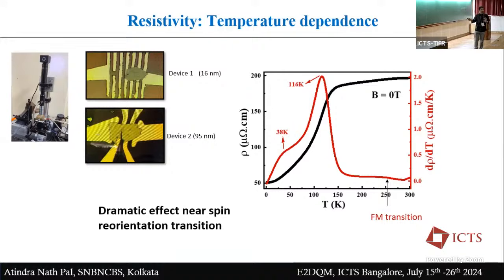Okay, there is a very weak signal. But if you come closer to the spin reorientation transition, which is around 100 Kelvin, 120 Kelvin, you can see there is a dramatic fall of this resistivity curve. That means it becomes more metallic. Okay, so then you can see also in the derivative, you can see two peaks. Basically, one is around 116 Kelvin, and another small hump we observe near 38 Kelvin.